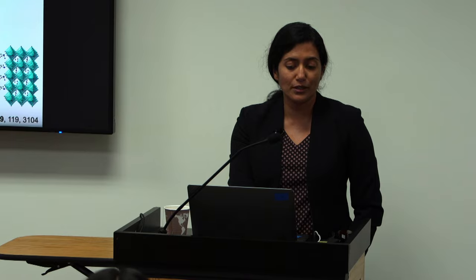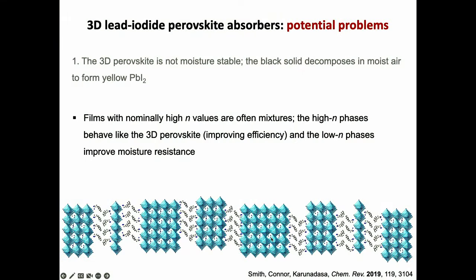So the idea is that if you have a mixture, and you very often do when you spin coat these materials, there are areas which look almost like a 3D perovskite, and that will absorb light and generate current just like a 3D perovskite. But every now and then, you're going to see these layers that are thinner, and these thinner layers are going to come with more organic molecules. And that's going to bolster the moisture resistance of this material. So we were pretty happy that we were able to improve the moisture resistance of this material.